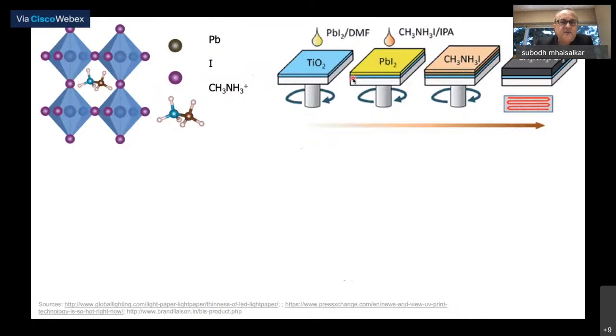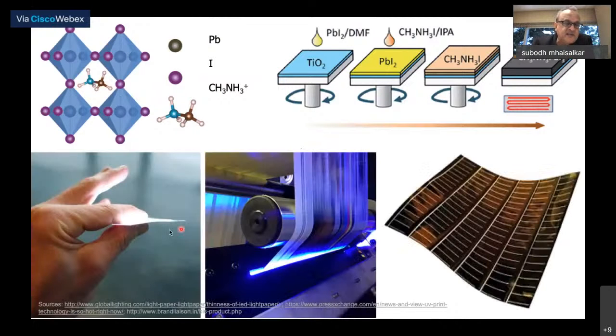One of the key attributes of perovskites is that it can be completely done in solution processing. And as you can see in this schematic on the right hand side, you can start with deposition of lead iodide and convert it using methyl ammonium iodide to methyl ammonium lead iodide perovskites. And this process can be done at less than 100 degrees centigrade. One of the key advantages is this can be done with really paper thin layers. It could be done with roll to roll processing.